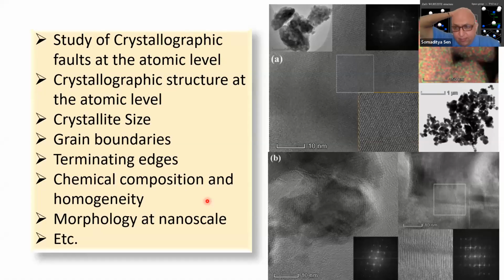So these are some examples of my samples. You can see there are crystallographic defects here, and there is one region, then a striped region here, and again another striped region. So there's a continuous discontinuity of this. This is a ferroelectric material, by the way, and the ferroelectricity is compelling the domains to keep on switching their orientation. Now the study of crystallographic faults and the crystallographic structure at the atomic level is also possible. In X-ray diffraction you cannot do it at the atomic level because atomic level information is not obtained. But here you can take a diffraction pattern of one grain and then understand the atomic structure. Then the crystallite size can be obtained from those images, and then the grain boundaries and terminating edges.